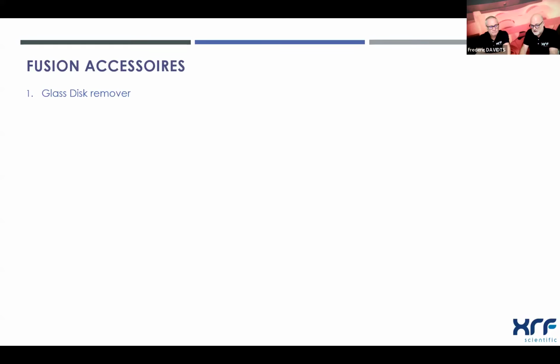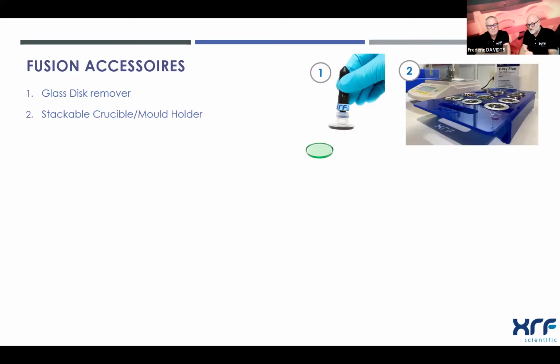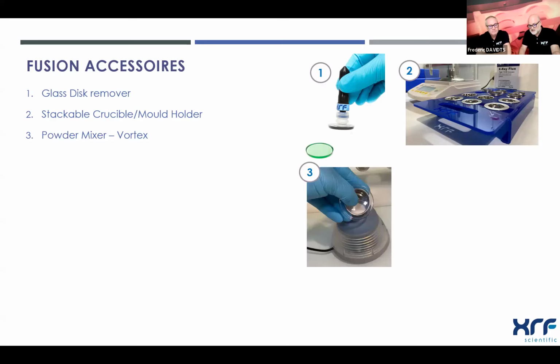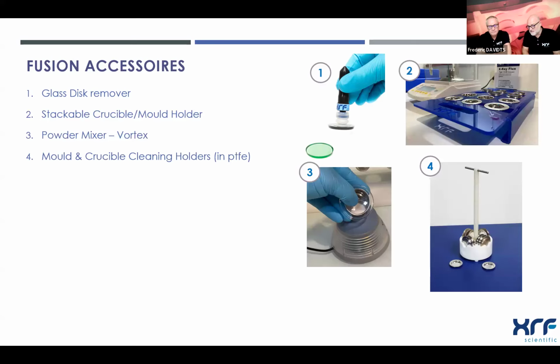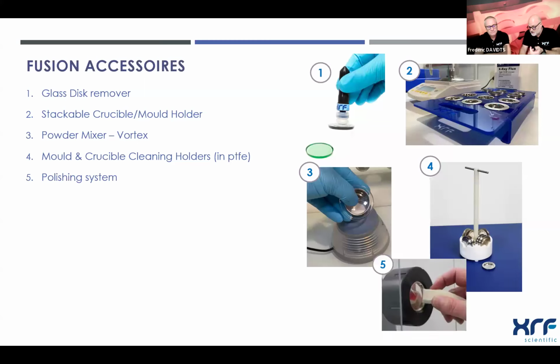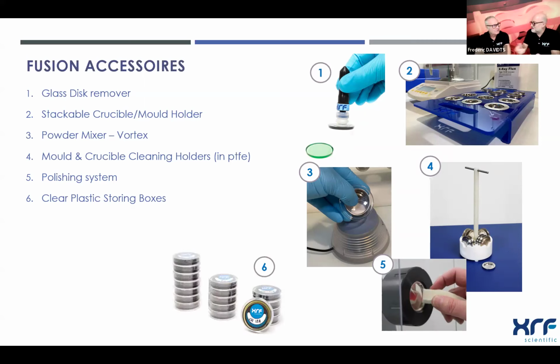So the fusion accessories are there to improve the whole process, and then you can have the glass disc remover. You can have a system to hold the mold and the crucibles, again to protect the surface of the mold. A vortex mixer, I really recommend it to mix the sample with the flux. It's very practical. And then you have some Teflon system that allows you to clean the mold in the ultrasonic bath without touching the mold surface with tongs, for example, and destroying the analytical surface again. We have a system to polish the mold, and then also a system to store the glass discs for a long time and avoid scratching them together.